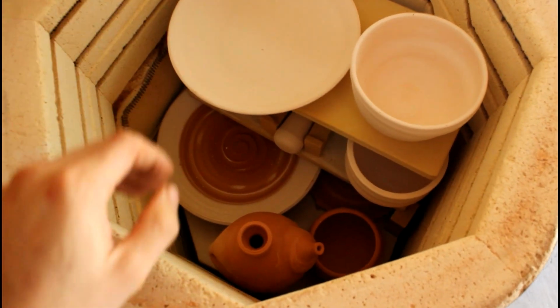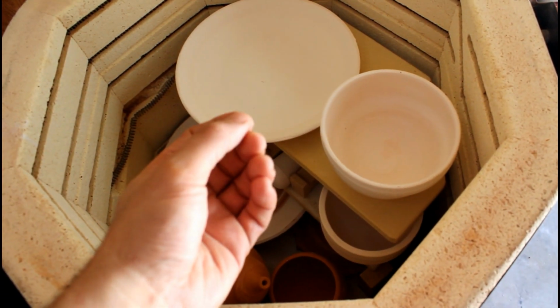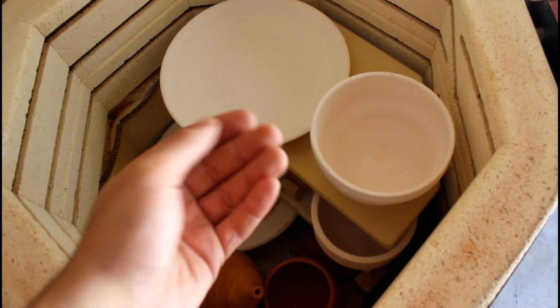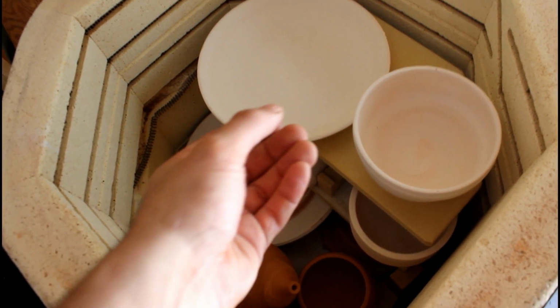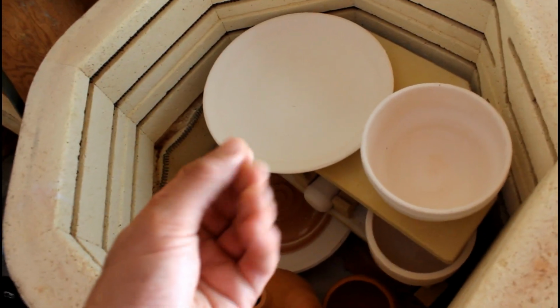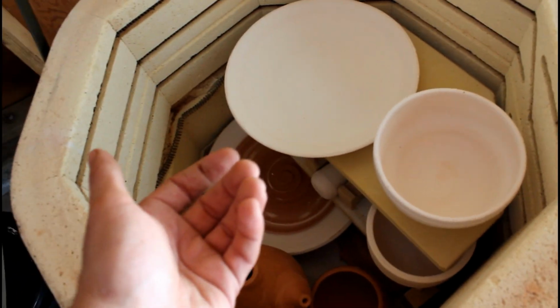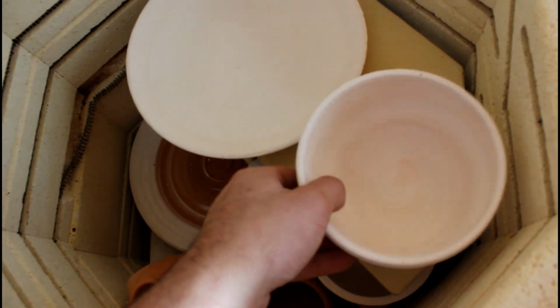Aw yeah, still good. No cracks. Pottery tip. Make sure that you wash your dirty little human hands before you touch bisqueware, because human oils that accumulate on fingertips, or anywhere for that matter, repel any glaze that you might get on your bisque. So if you're taking this straight out of the bisque with your dirty chicken hands and you're about to glaze something, don't be surprised if your glaze crawls,